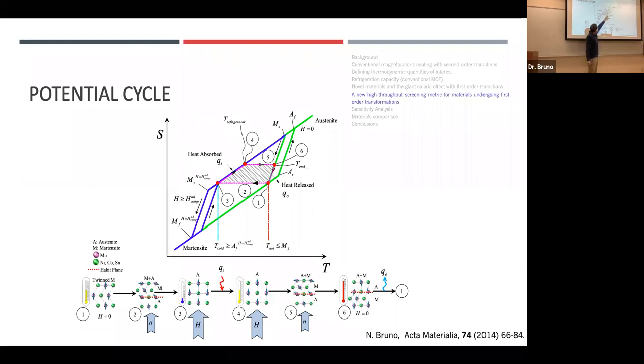So we start at the martensite finish temperature, we apply a magnetic field, generates cooling, we absorb energy, we release the magnetic field, and we can do it again and again. But the stipulation is we need that hot temperature reservoir of our thermodynamic cycle to be at the MF temperature. That way, when we come back to it, we can then ramp field again and do it again and again and again. That would be equivalent to our ferromagnetic material that does not exhibit a first order phase transformation.